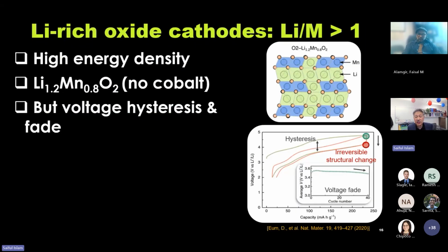So let me introduce one of the exemplar or model systems. This is the Li1.2Mn0.8O2 lithium-rich manganese cathode material. I'm showing you the structure on the top right, which shows the lithium in green. So it's a side view, and then the transition metal layer in blue. And you can see there are some lithiums in the transition metal layer, hence lithium rich.